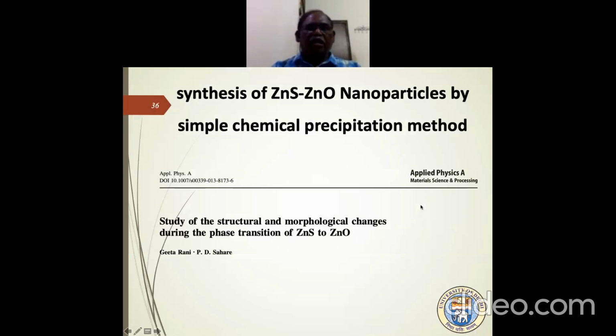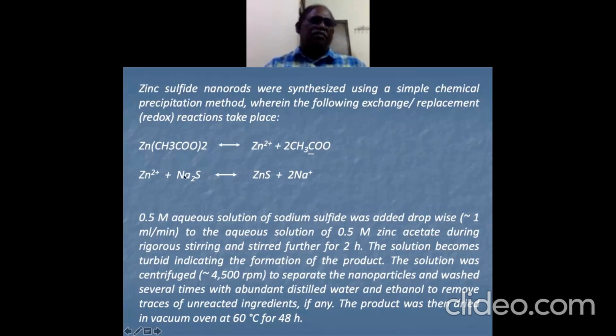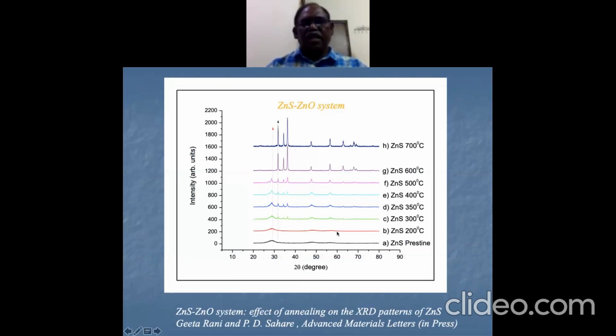Then we wanted to do some band gap tailoring over here. So we have studied the ZnO/ZnS composite system. And again we have the same very simple technique of co-precipitation method. And you can see that in the XRD, you have this ZnS here, and if you go on annealing it at different temperatures, this ZnS gets oxidized, and you also get another phase, that is the ZnO phase over here.